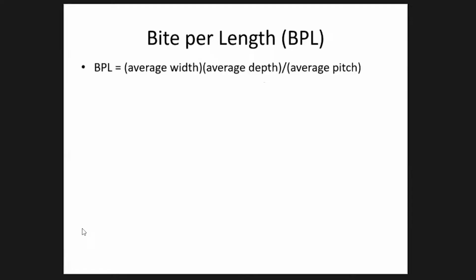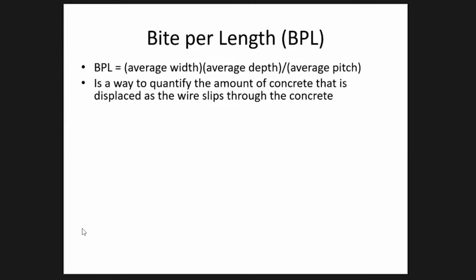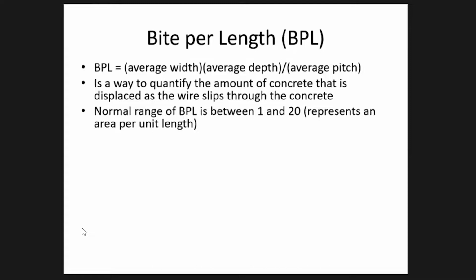So the term that I coined is bite per length. Bite per length is simply the average width of the indent times the average depth divided by the average pitch. It's a way to quantify the amount of concrete that's being displaced as the wire slips through the concrete. We know in the transfer length there's relative movement. We can actually measure an end slip of the wires when we detension them. The normal range of bite per length is between about 1 and 20. It's actually in units of millimeters squared per inch of length, which people don't like as a unit, so I just say it's a relative unit, 1 to 20.